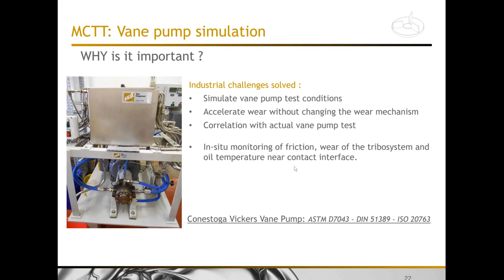The first line contact application we'll show is the simulation of a Conestoga-Vickers vane pump test. These are component tests for hydraulic oils focused on anti-wear properties of hydraulic fluids. The downside is that these tests take very long and require a lot of oil. The ASTM test takes 100 hours; the ISO test takes 250 hours. So it's expensive both in cost and time, and it would be nice to have a laboratory scale test that can predict or pre-screen oils for this component test.